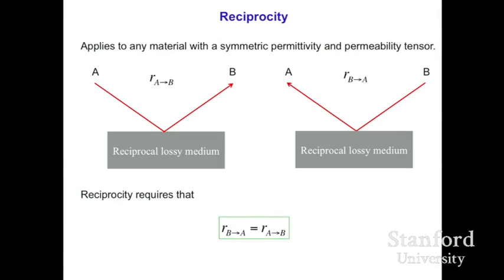So, to review that, it will be useful to consider a standard reciprocal lossy medium. All the structures I've talked about up to now, for example, are standard reciprocal lossy media. And then imagine these are in thermal, radiative contact with two black bodies. If you have a black body A emitting down, you have a reflectivity to black body B here. And if a black body B emitting down, we have a reflectivity to black body A. Then reciprocity will require that these two reflections are actually the same. And so consequently, you can show that the emissivity and absorptivity have detailed balance.